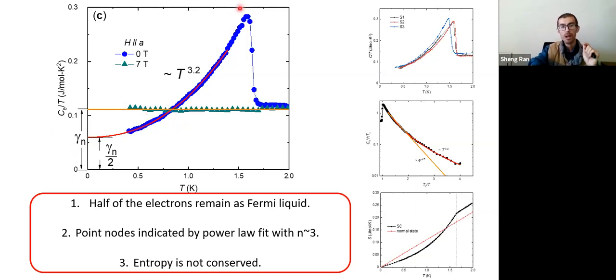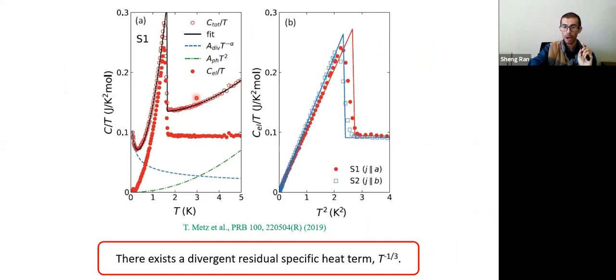All right. The second thing is, below the superconducting transition temperature, if it's a BCS superconductor, the specific heat should really go as an exponential law. But here it goes as a power law, and the power is like T cubed. So that indicates there is a point node. And the third thing you might notice is the entropy is not conserved. If we take the integral beneath this curve, that gives you the entropy. But notice this portion and this portion, in an ideal case, they should be balanced, but here the entropy is not conserved. So what's going on?